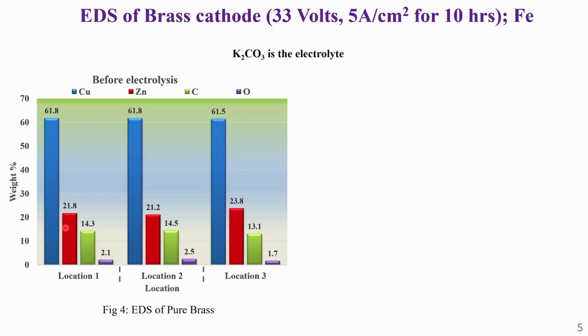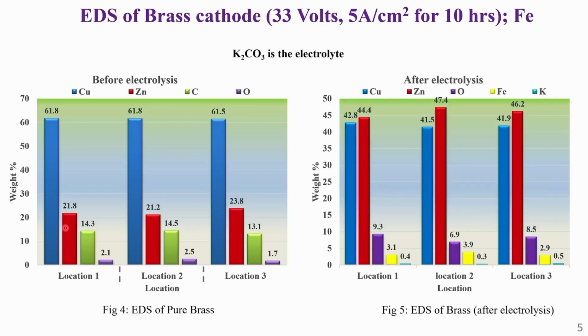whereas figure 5 shows the EDS analysis of reacted brass. After the electrolysis process, we again get a new element, 3 to 4% iron, as a transmutation in the yellow color bar, and a significant increase of zinc is observed.